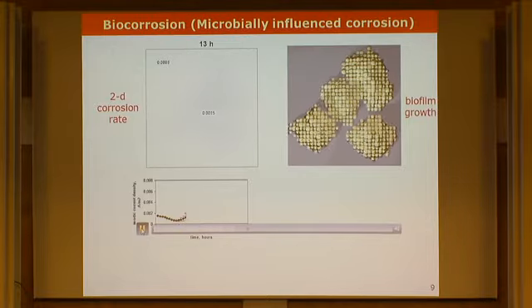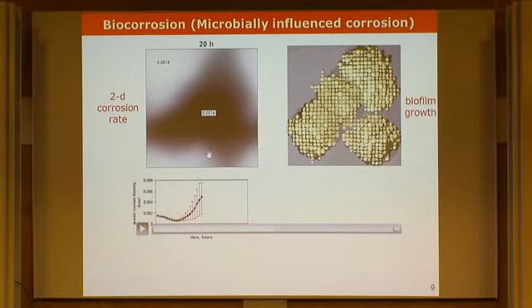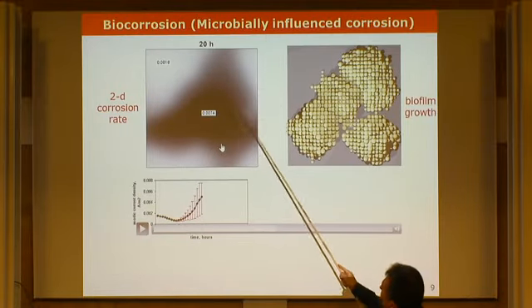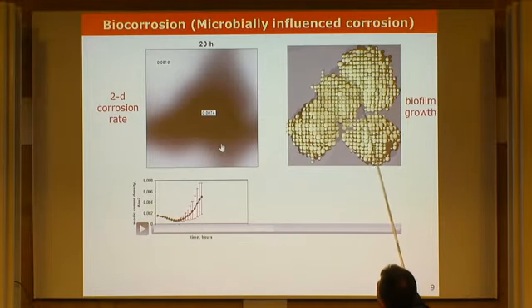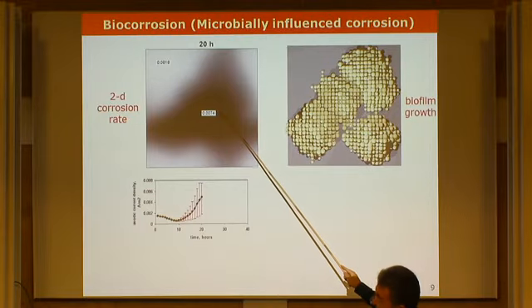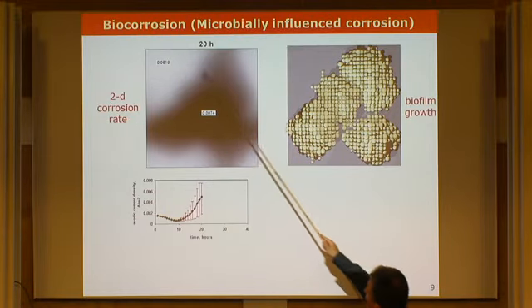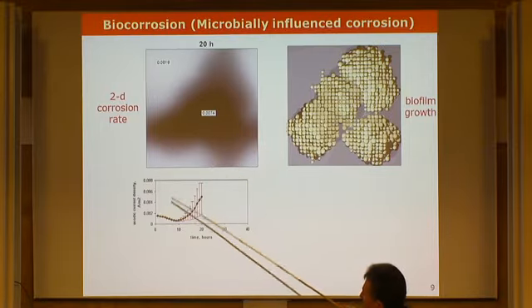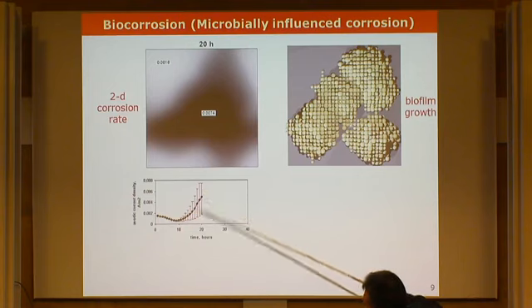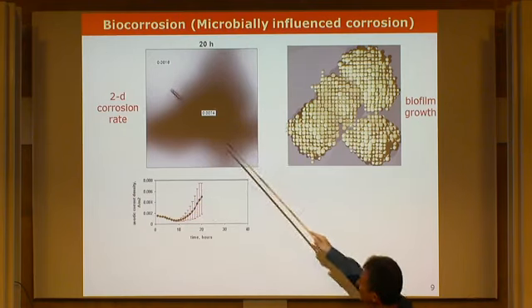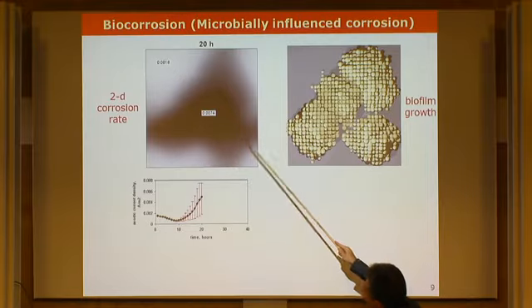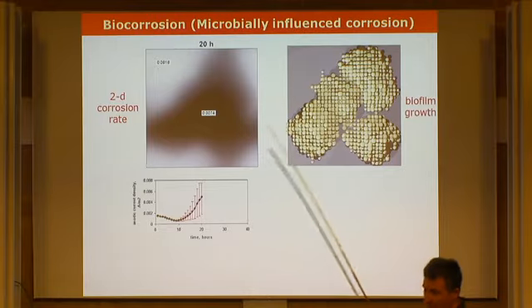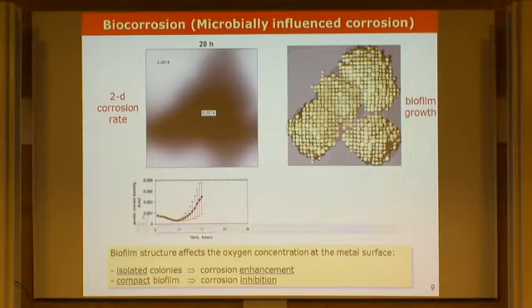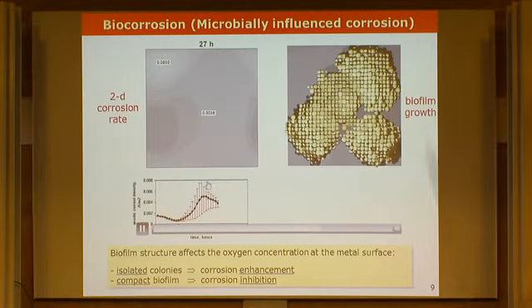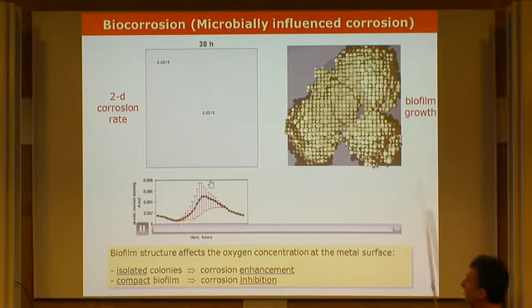So this is quite interesting. If we stop somewhere here, you will see large differences. Under the biofilm, you have a high current, high corrosion. This is pitting here, pitting corrosion. While outside, there is less corrosion. And this is practically the total corrosion, and all these error bars show you how non-uniform the corrosion is. So this is now pitting corrosion, localized corrosion. If the biofilm grows further, something very interesting happens actually, because the corrosion rate decreases now.